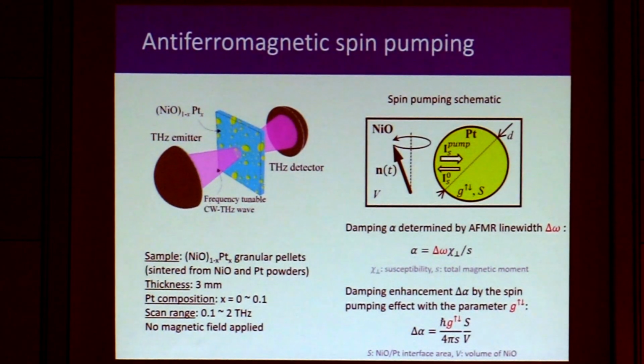Yeah. That's why my question is, if you apply a magnetic field, the spin current will not be cancelled. So there will be an effective spin current coming in also in an antiferromagnet. This might be a way to measure it. Okay, yeah, I'll try. Yeah, you can still have spin current in that case, but provided you have circularly polarized antiferromagnetic modes, and that's the open question in nickel oxide. I believe there is a published work where the authors, in a theory analysis, claim that nickel oxide actually has linear polarization, which does not give rise to spin. So you need right-handed or left-handed antiferromagnetic modes, chirality in the antiferromagnetic modes, in order to get spin pumping. And that is an open question for nickel oxide because of the biaxial anisotropy.